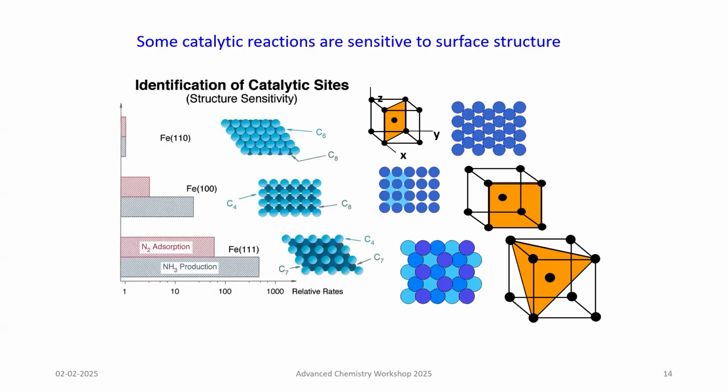In the modern studies, why iron is actually active is a question that has been addressed. What people have done is, they have taken iron 110 crystals, iron 100 crystals and 111 crystals, small crystals, not a regular material, but small crystals oriented in these planes, and then loaded them in a small reactor, put some 15-20 crystals and carried out the reaction, ammonia synthesis.